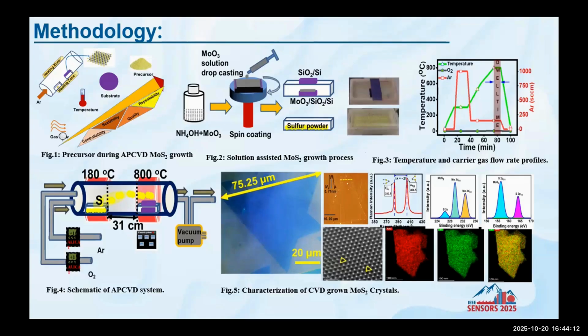So this is the optical image of single crystal MoS2 grown by this APCVD system, and its further characterization to investigate its topology or thickness, which shows 0.71 nanometer thickness, highlighting that it is a monolayer MoS2. For further validation, we did Raman spectra, which show the in-plane and out-of-plane peak difference between the two peaks, further confirming that the deposited triangle is monolayer MoS2. For elemental validation, we did XPS analysis, and this is the STEM analysis for the elemental distribution of Mo and sulfur.